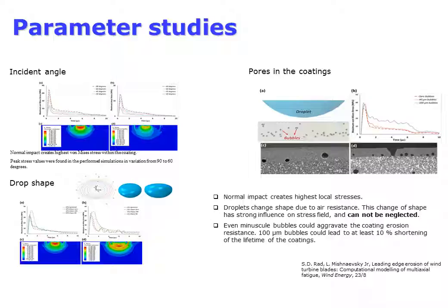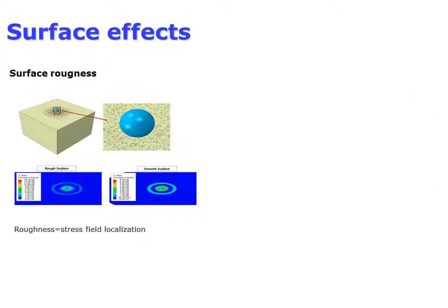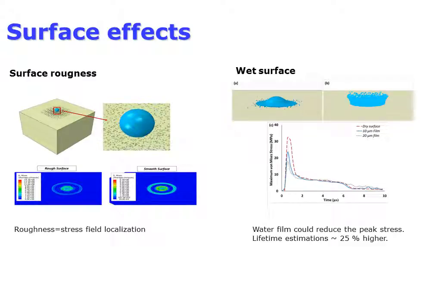Further, the void effect was studied. Even small voids in a coating drastically reduce its erosion resistance. Further, surface effects on the erosion were studied, in particular surface roughness and the availability of liquid film.